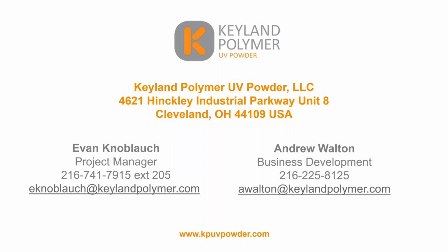What types of applications or industries are you seeing the most interest from for this technology? Well, actually, the ones that we laid out: the aerospace, automotive, and sports recreation equipment industries are the ones that we're seeing the most work in for UV curable powder coatings on both plastics and composites. What is the particle size distribution of the powders? It varies, but it's typically about the same particle size as a traditional thermoset powder coating, so 35 to 45 microns.